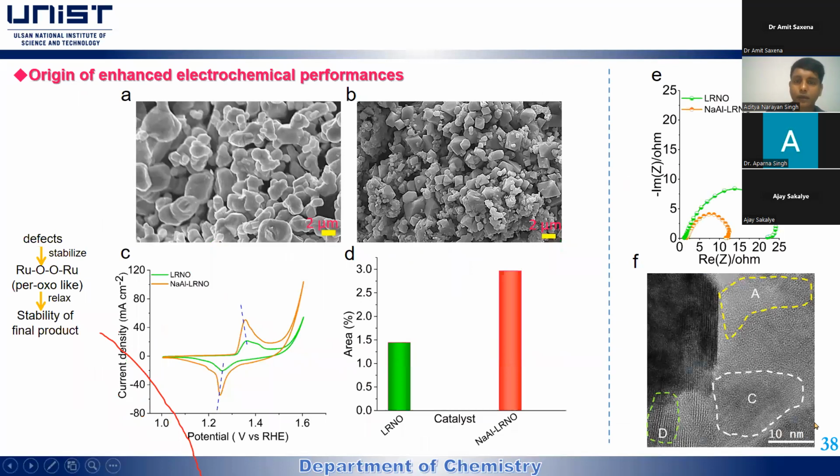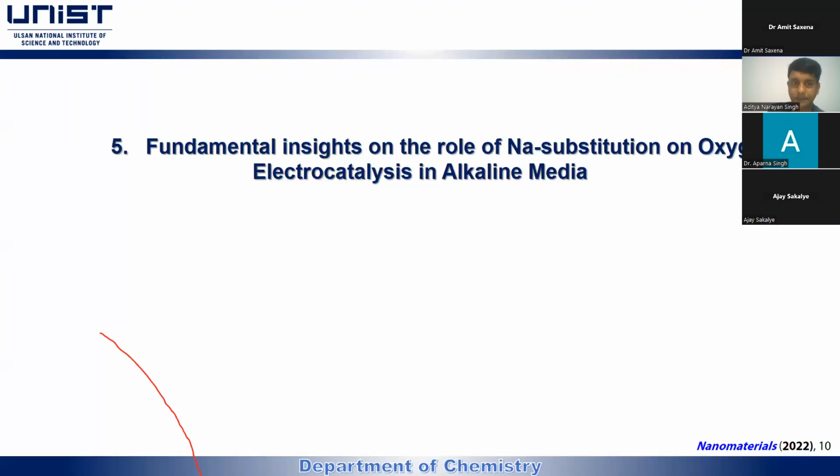So this is simply because we encountered faceted structures, and faceted structures have a larger area for surface reactivity or surface chemical reactions, mainly which happens in water splitting. You could see there are amorphous zones and crystalline zones, and there are defective zones. It's simply that when you dope individually, you encounter certain different chemistry. When you dope together, you encounter certain different chemistry. So care must be taken when you go for doping.